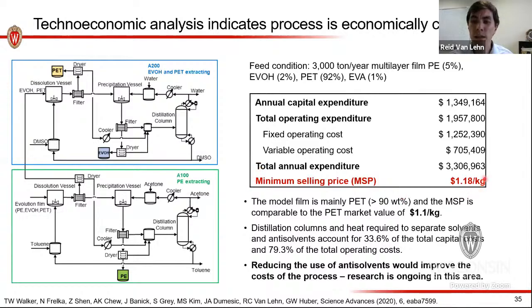We get a minimum selling price. So this is how much we have to sell the material for us to break even, of about $1 per kilogram. This is actually great news because if I were just to try to buy the major component of this film as a virgin resin, it's nearly the same price. So once they get up to 3,000 tons per year, which is still a very small number compared to the amount of post-industrial waste we generate, we find that our process is economically competitive. And moreover, we found that we can even reduce the price if we remove some of these processing steps by using things like temperature changes rather than anti-solvents to precipitate out our film.